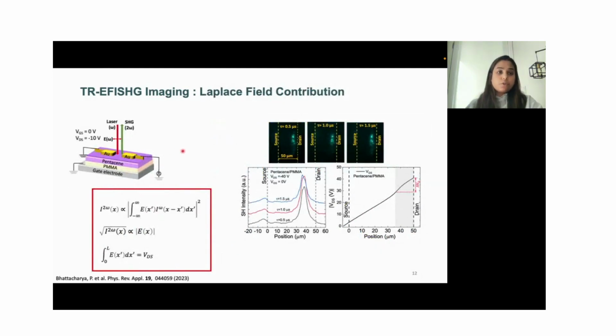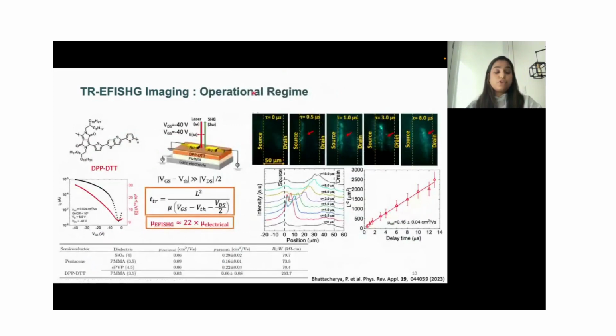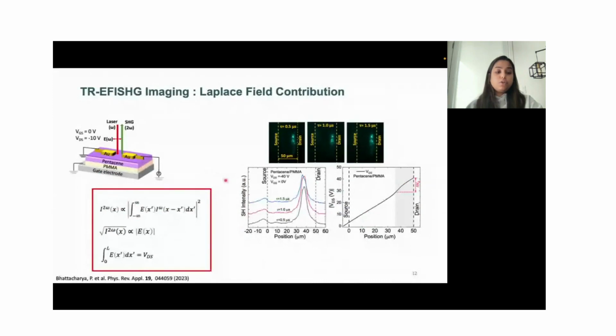In terms of other non-operational regime applications, the Laplace field contribution, or the contribution due to the applied electric field, can be directly mapped from EFISH imaging, as you can see here. And this is particularly useful in deconvolution of the Laplace field contribution when we operate them in the operational regime, which is supposed to be a combination of the Laplace field contribution due to the applied field and the Poisson field contribution due to the motion of the electrical charges. So that again helps us in the deconvolution of the Laplace field contribution from the total contribution.